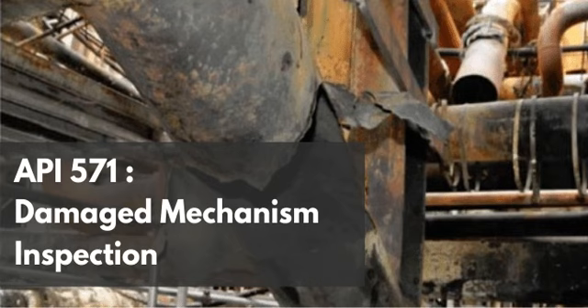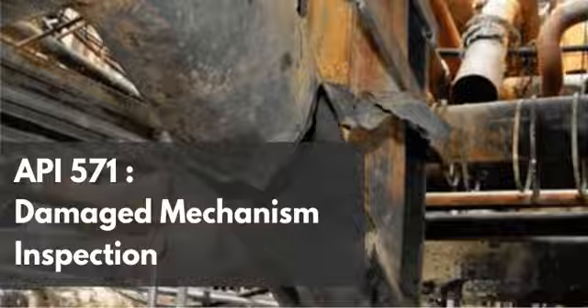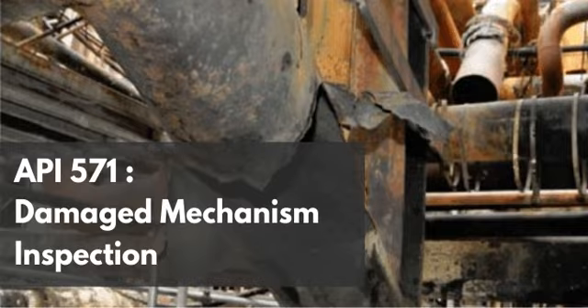Man. So we've basically manufactured our own poison here. Yes, exactly. We've taken a chemical designed to protect our downstream assets from acid gas. We've overheated it in the presence of the very gas it captured and created an acid that eats the pipe holding it. That is the tragic irony of amine systems right there. It really is. And when this newly formed acidic soup attacks the steel, it doesn't just dissolve the metal in one uniform, predictable way everywhere, right? No, the morphology is very distinct. Right. The physical characteristics of the damage.